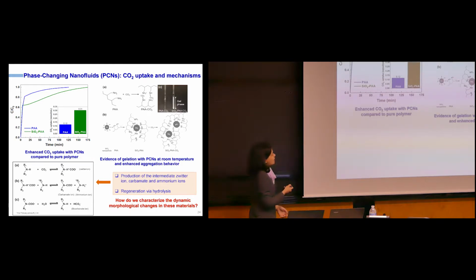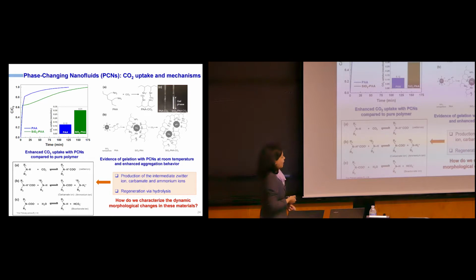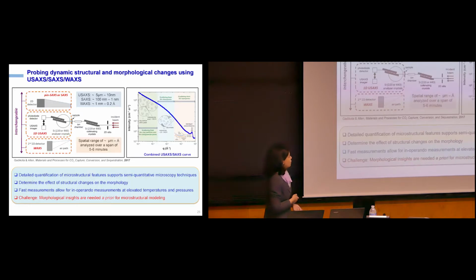What is also interesting is that when we have these SiO2 molecules, SiO2 with PAA bound, we actually get higher CO2 uptakes as well. And this is not only because of the CO2 binding to the functional groups, but the CO2 actually getting trapped in some of those interstitial spaces also. So there's an entropic effect on top of the enthalpic effect. And we can also regenerate these hydrogels. If you just pump a lot of water, they tend to get hydrolyzed, and they tend to get regenerated as well. So in sum, you could call it effectively a reversible fluid, if you like.